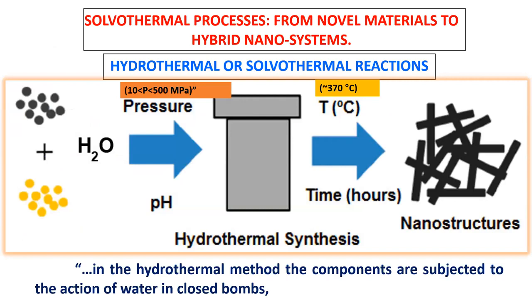In the preparation step, we are using solvothermal processes for the hybrid materials. If your solvent is water, the procedure is called hydrothermal synthesis. As you can see in the figure, we can prepare our solid phases, which will be hybrid materials, with water. In a Teflon bomb, we use pressure and temperature at suitable pH, and sometimes, for example, 2 or 3 hours later, new nanostructures will occur. This system is called hydrothermal synthesis,